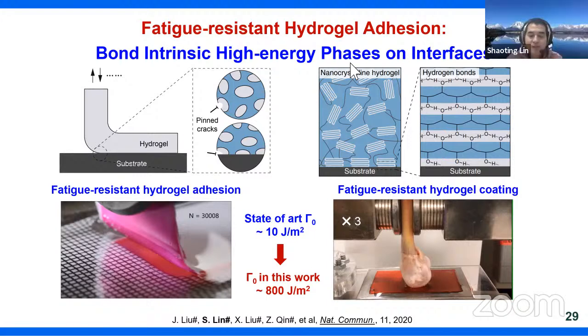Let me explain. There are two failure processes for hydrogel adhesion detachment. One is so-called adhesive failure, and the other is cohesive failure. Adhesive failure is failure at the interface. Cohesive failure happens in the material. If it is cohesive failure, then it is essentially the same as the bulk material. If you look at this schematic, these crystal domains form extremely strong hydrogen bonds with the substrate, especially the glass substrate. Due to the synergy of these strong hydrogen bonds and the surrounding high crystal domains in the bulk material, we achieve a high fatigue threshold.